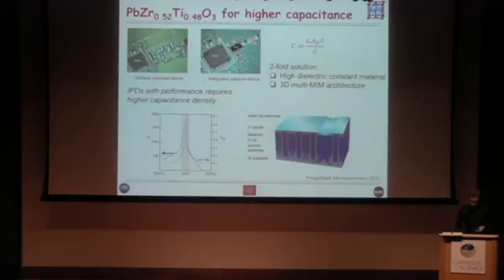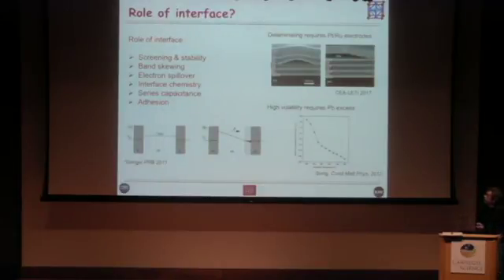Now, it's not that simple, obviously, and in particular, the role of the interface is very important. Do the electrodes that you use provide sufficient screening to stabilize the ferroelectric state, or is there a remnant internal field? If the electrodes are asymmetric, are the bands skewed, changing the band structure of the capacitor? Do electrons spill over from the electrode into the dielectric, basically meaning that you're metallizing a thin layer, or at least creating an altered thin layer? Is there a specific interface chemistry? And then there are other questions such as adhesion.